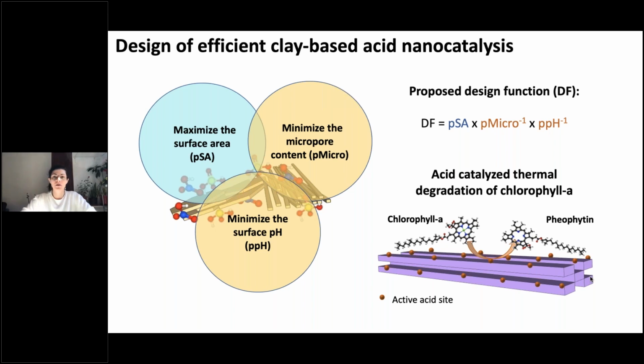Through this design function, we want to rapidly screen the possible modifications, finding the best balance between maximizing the surface area while minimizing the micropore content, which is typically not accessible to the substrates, and maximizing the surface activity, which in our application means minimizing the surface pH. Then we extracted the top promising modifications, and we prepared a prototype and tested it in an acid catalyzed thermal degradation of chlorophyll A.